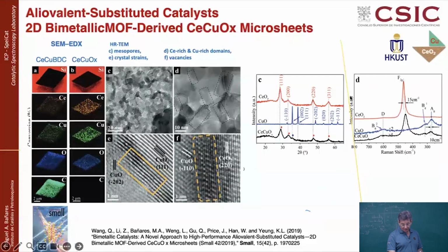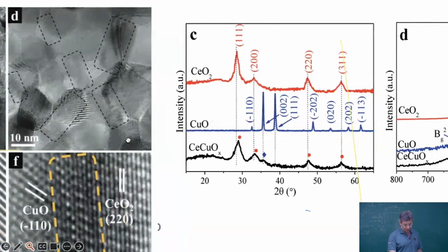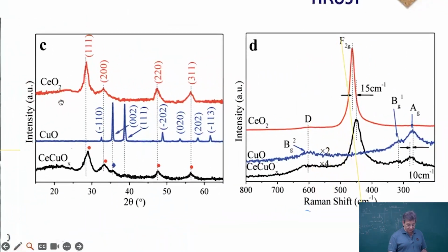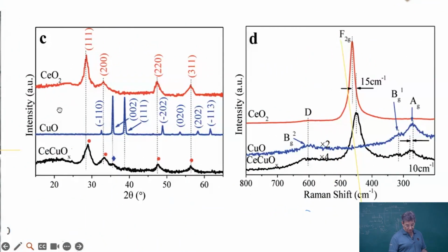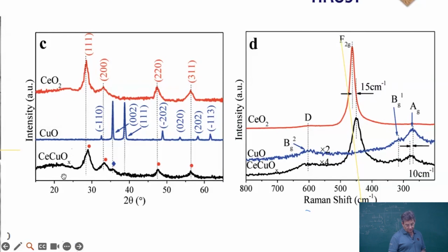And even the characterization of the system, when you are looking at both the Raman and the X-ray diffraction: in X-ray diffraction, reference ceria looks like that, reference copper looks like that, and this oxide generated by the decomposition of the MOF looks like this. You have some bands, you see some distortion, and essentially it looks like ceria, but there is some distortion. You may think that this is probably one peak from copper, but very small domains, highly amorphous.